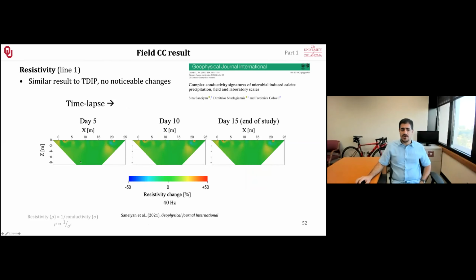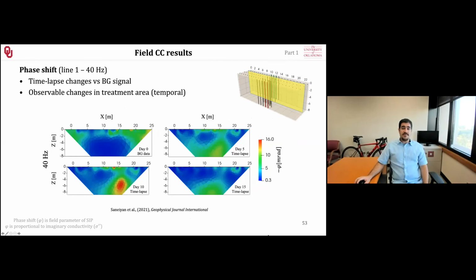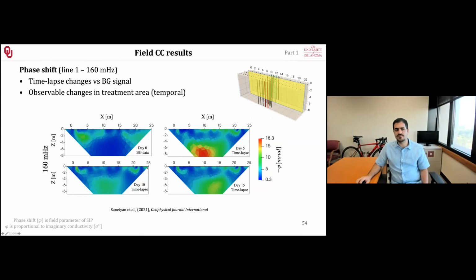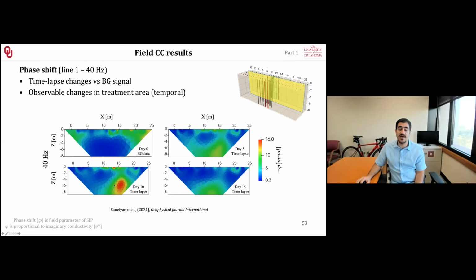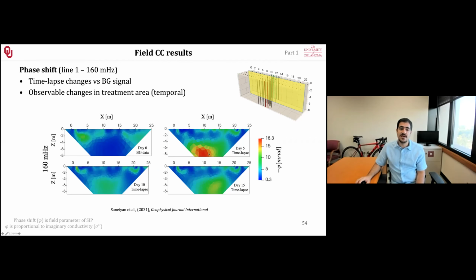So over time, we're not seeing anything. But if you use the phase shift and basically do a time-lapse analysis, we are clearly seeing at the same area the increase in the signal is observed at higher frequency as well as lower frequency. So we are seeing a difference in here. The peak of the signal at higher frequency is different than the lower frequency.